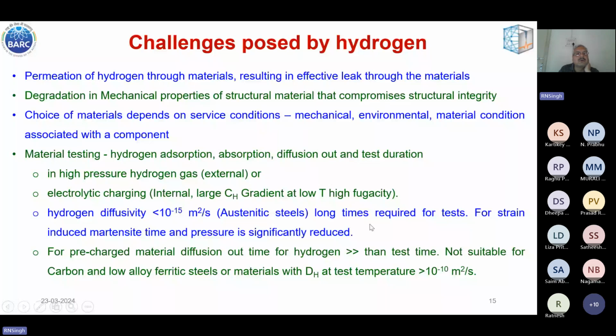However, for strain-induced martensite, time and pressure is significantly reduced. For pre-charged material, diffusion out time for hydrogen should be very, very large compared to the test time. Otherwise, if the test time is longer, hydrogen will diffuse out and the effect of hydrogen will not be captured. So this method is not suitable for carbon and low alloy ferritic steels or materials where diffusivity is higher than 10⁻10 meters per second.